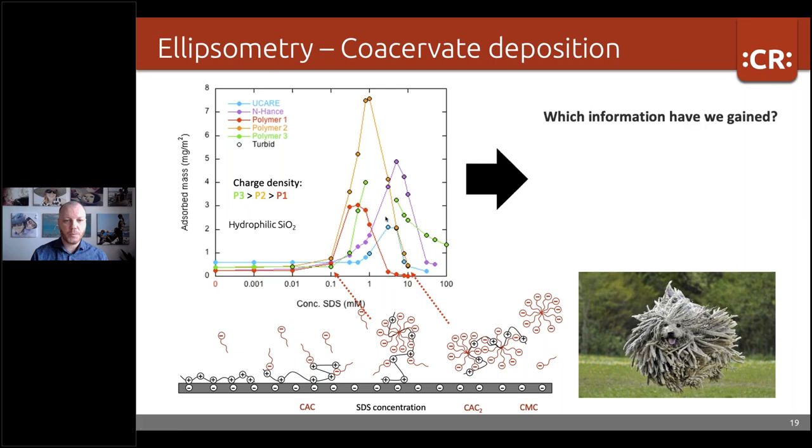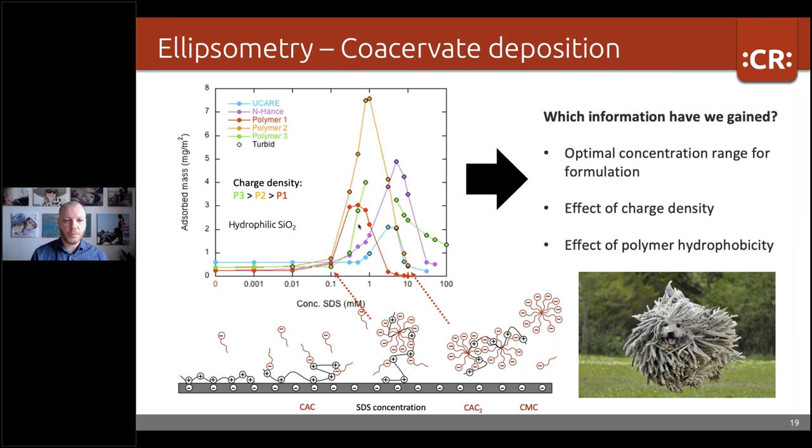So the information that we can gain from this is the optimal concentration range for your formulation. So you want to be close to the deposition limit on this side here with your shampoo formulation, so that when you start to dilute in the shower, when you rinse, you go quickly into this deposition range here. You can also see the effect of the charge density of your polymers. So they had different charge densities for these three, and that will determine a bit where this window will be found. And also some information about the hydrophobicity of your polymer. For instance, the N-Hance here is more hydrophobic than the other polymers,